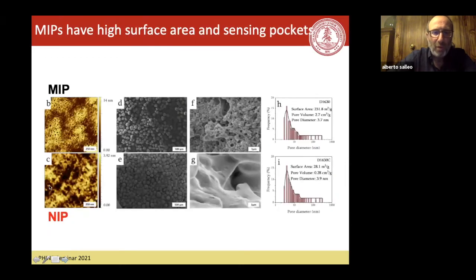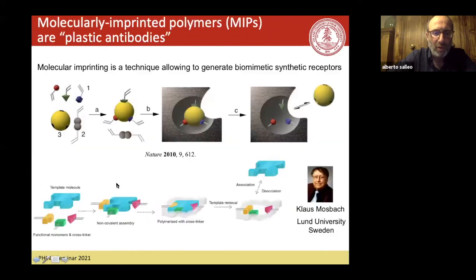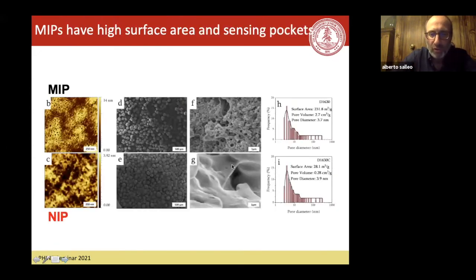And so we make our molecularly imprinted polymer. These are particles. This is what they look like. They have a lot of pores. And then we also make a non-imprinted polymer, where we use the same molecules, but we don't use a target molecule. So we have the functional monomers, the cross-linkers and all that, but no template molecule. So there's nothing to mold around. So these now have a much lower surface area, as you can see.